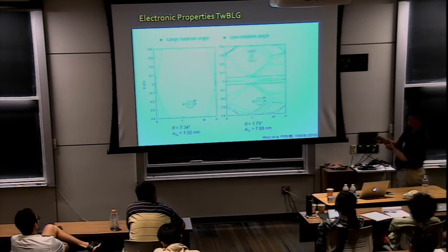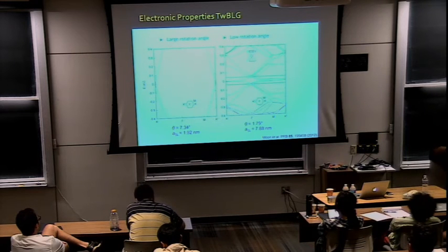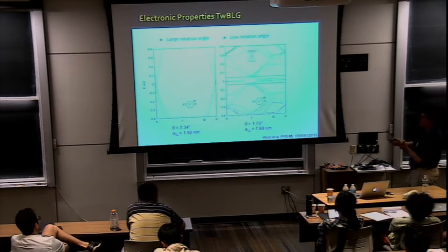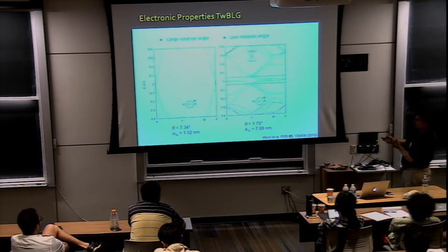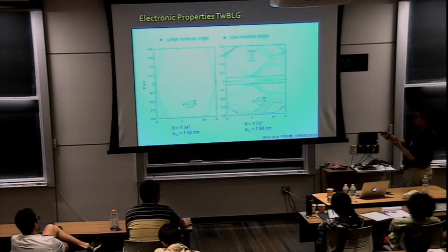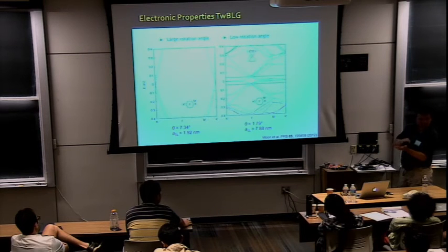This is the actual spectrum of twisted bilayer graphene, 1.8 degrees rotation. You can see it's completely reconstructed. It has nothing to do with what it had before, right? You can see, if you want, those straight lines are what remains of those original straight lines, a massive change in the Fermi velocity. Okay? In addition, you have these superlattice structures associated with the Moiré potential, which are gapped. They don't form Dirac points because this is graphene on graphene, not graphene on HBN.